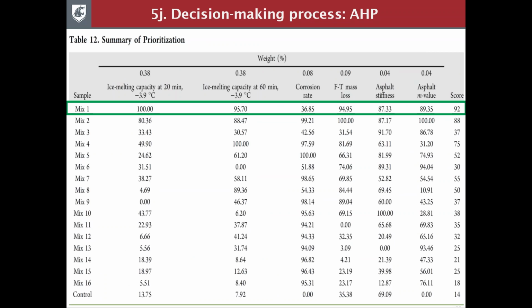So when we look back at the 16 mixed designs versus the control, we can then basically multiply the decision weight table with the actual experimental data and come up with a composite index. Of course, before we do that, the experiment data was normalized between 0 to 100 for every parameter. So in this case, we end up with one mixed design being the best formulation with a score of 92 out of 100, which means really good balanced performance and impacts.